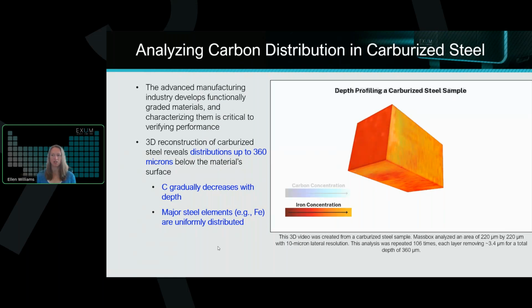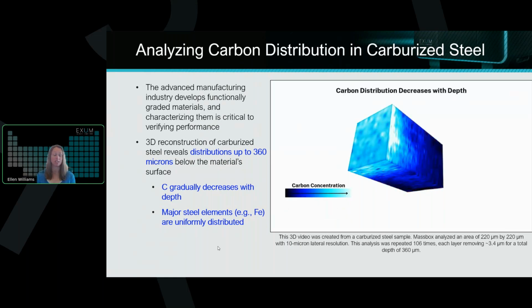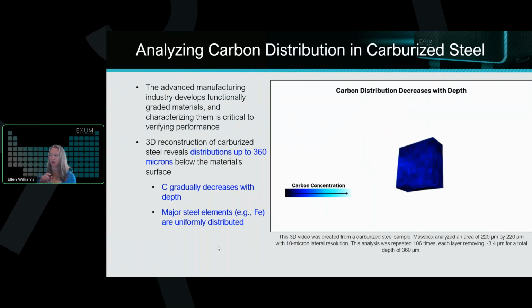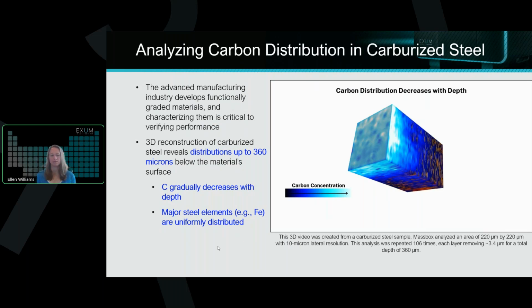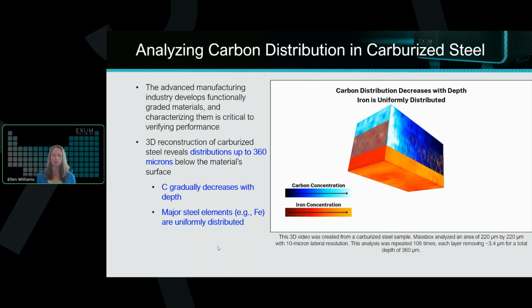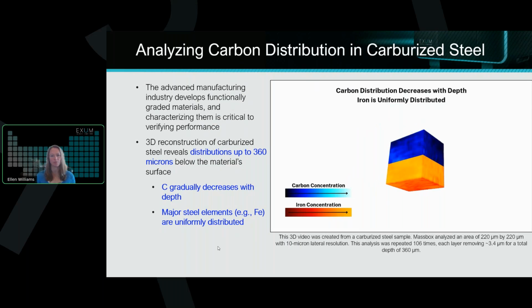And in this case, we were trying to get to this very deep depth. And so we chose to increase the laser power and overlap the spots so that we're removing about 3 microns of material per layer, and allows us to again get this very deep depth profile. So, it is material dependent, but there is some flexibility there, and it can range from tens of nanometers on the low end all the way up to single-digit microns on the high end.